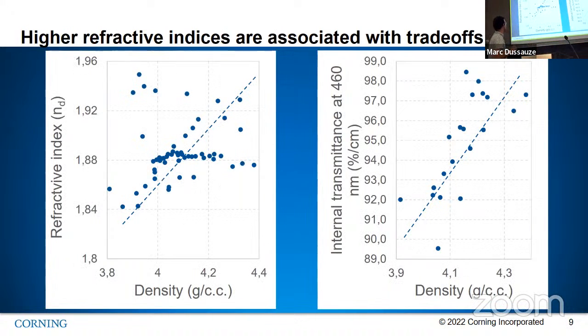Just to show you some examples of the situations we're facing. If we look at the refractive index versus density, you see that usually as we increase density, the refractive index is increasing. We have some points on the upper left corner that are not following this trend. That's when we're using different combinations of elements in the glass to try to minimize density. But usually those points, as I told you, are going to be glasses which have lower transmittance, so they're not going to be interesting for us. So the work then is really to find the right balance to have the best of all of the attributes.